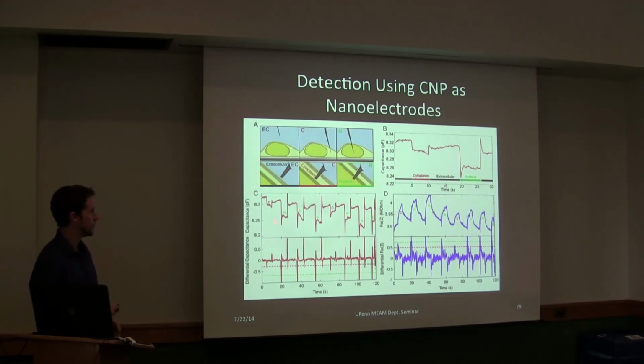You may also wonder what this peak right here is. So if you fit a time constant to this transient right here, you get about 0.3 seconds, which perfectly matches the literature value for relaxation time of the cell membrane. So we believe it's due to relaxation of the cell membrane. There could also be a Cottrell current effect due to a jump in membrane potential across the cell membrane. But we can detect cell penetration.